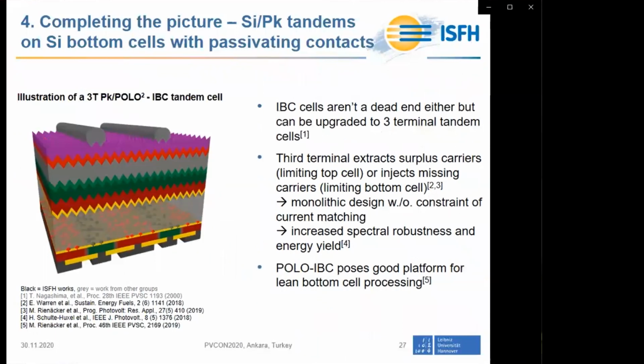Also, IBC cells can be combined with perovskite top cells, and this results in a very interesting tandem configuration, which is shown here. It's a so-called three-terminal tandem configuration. Such a three-terminal tandem cell has one contact on the top and two contacts on the rear. And the additional third terminal on the rear gives you the opportunity to extract surplus carriers from the bottom cell in the case that the top cell is current limiting, or it can be used to inject missing carriers into the bottom cell in the case that the bottom cell is current limiting.